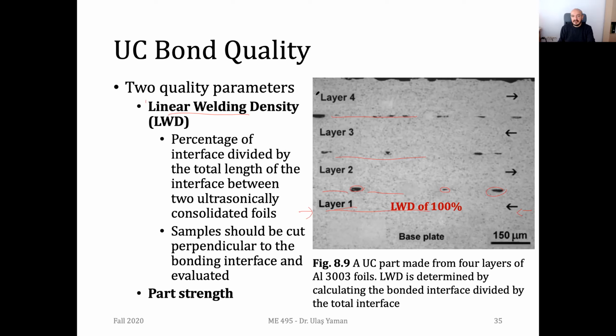Another thing is that if you look at the top surface, we have bumpy regions, right? This is the top surface, and why do you think we have such a case? It's just due to the force applied by the sonotrode and the system. And the surface roughness actually depends on the quality of your sonotrode and also the amount of force you are applying on the part.